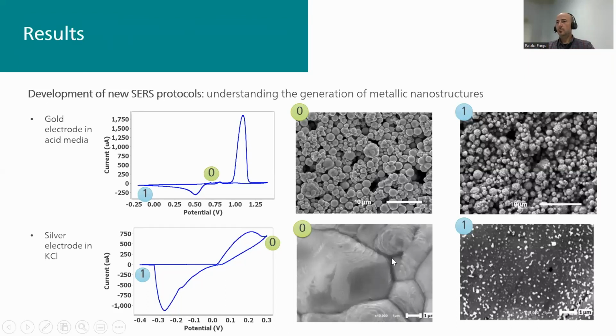Okay, so I will show you here a couple of electrochemical pretreatments that we usually carry out with gold and also with silver electrodes to get these SERS substrates for our standard applications. So if we work, for instance, with a gold screen printed electrode that initially has this surface structure, usually we oxidize it in an acid media, for instance, in sulfuric acid. We can go to positive potentials to plus 1.1 volt to get the oxidation of the gold, and also we can produce some dissolution of this gold. And then in the backward scan, we can reduce the gold oxide that we have previously generated.